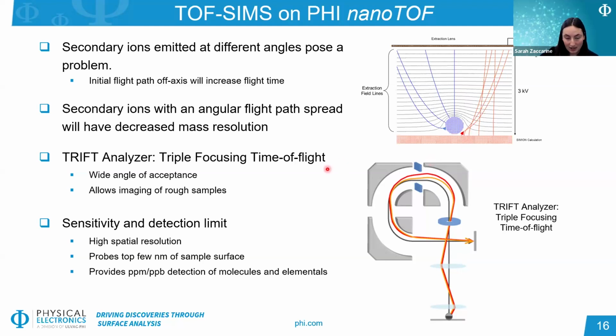However, on Phi TOF systems, we have a unique analyzer design, which is the TRIFT analyzer, which stands for triple focusing time of flight. If you look at the schematic here, the black line is representing the more normal ion path, but in this type of topographic sample, we're going to have ions coming off on the edges. This unique triple electrostatic lens focusing means that our ions will be compensated to reach the detector at a similar time and compensate for that wide angle of acceptance. So this allows us to analyze these types of rough samples with higher mass resolution.